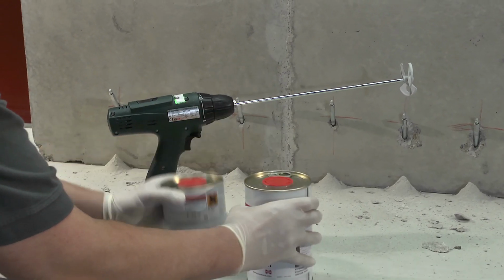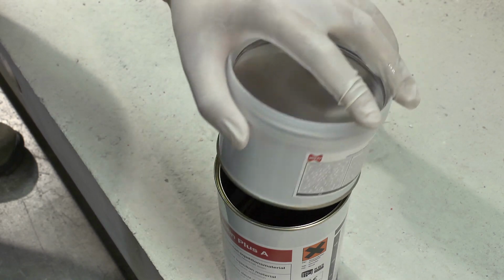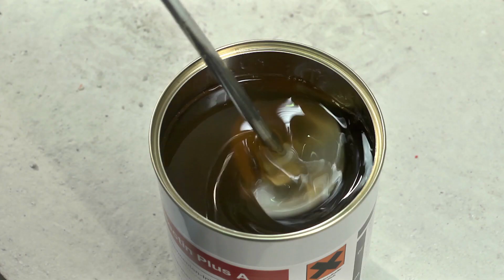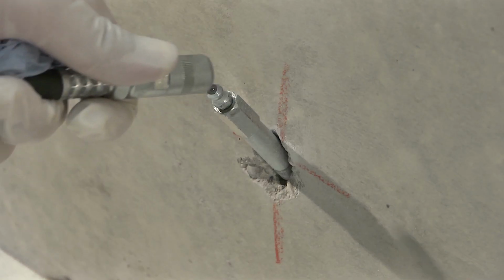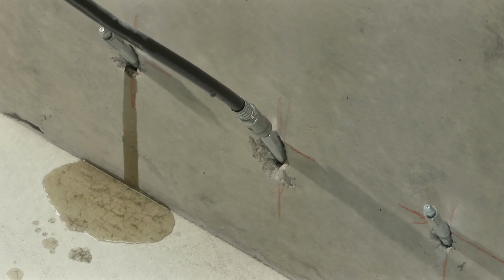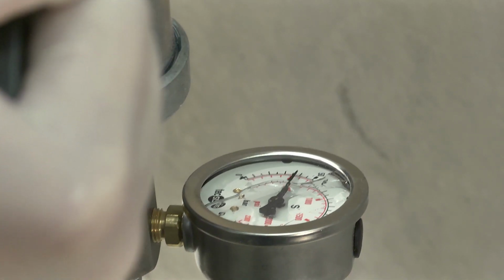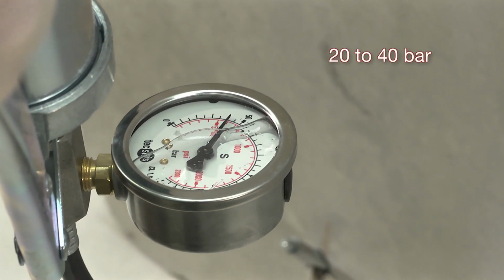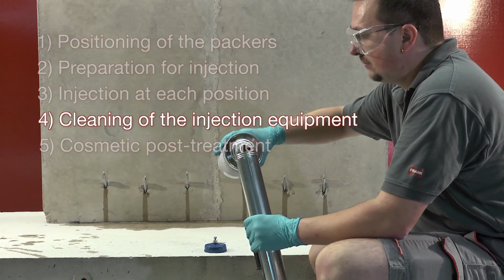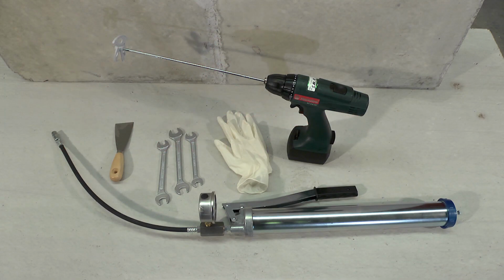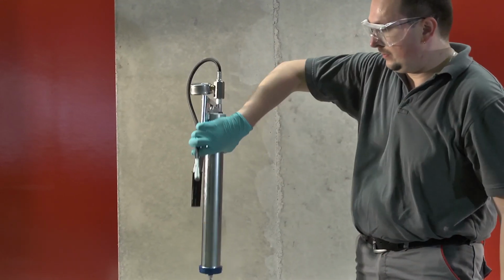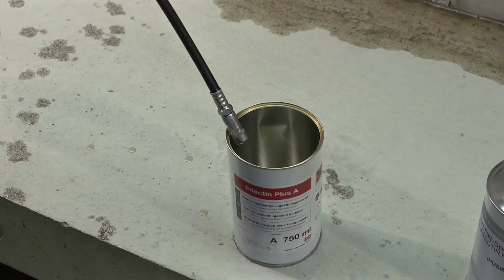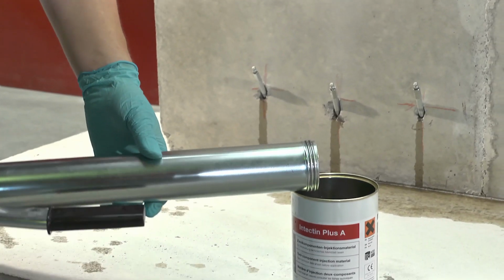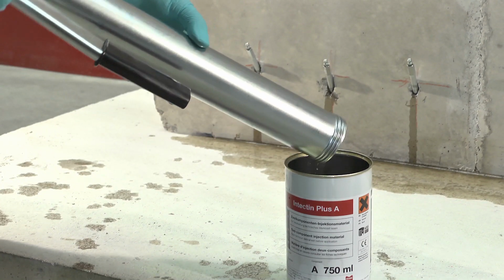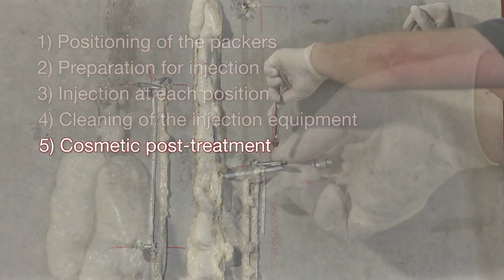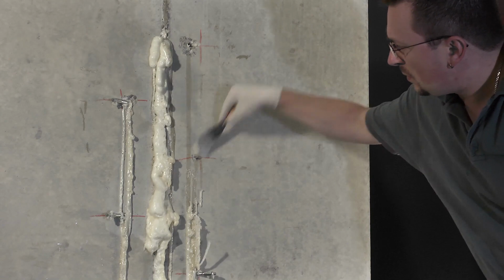To seal dry or moist cracks or joints, use Intectin Plus A only. After thorough mixing of the two component resins, several injections should be carried out in accordance with the project requirements until the crack or joint is filled completely. All injection work should be performed at pressures between approximately 20 and 40 bar. Depending upon circumstances, it may be necessary during the injection process to clean off any buildup of resin residue on the impeller mixer and pump using Intectin special cleaner. The final cleaning in phase 4 contributes to the durability of the tools. For phase 5, grouting residues are removed and the treated surfaces are post-treated cosmetically.